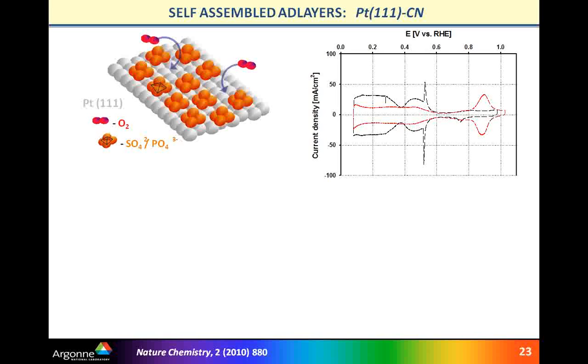The results, what you can see right now, is just something that we try to, as I said, keep the electronic properties of material, but to change catalytic activity by molecular patterning. In particular, this is the case for very slow reaction rate or kinetics of oxygen reduction in phosphoric acid fuel cells because of absorption of phosphoric acid anions.